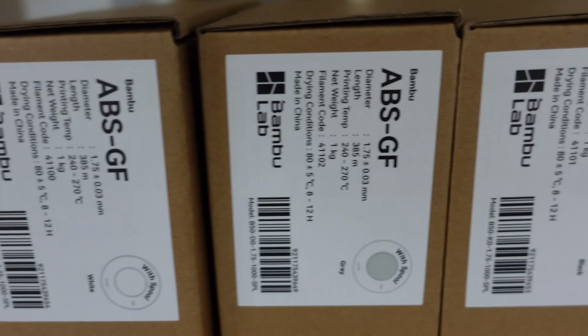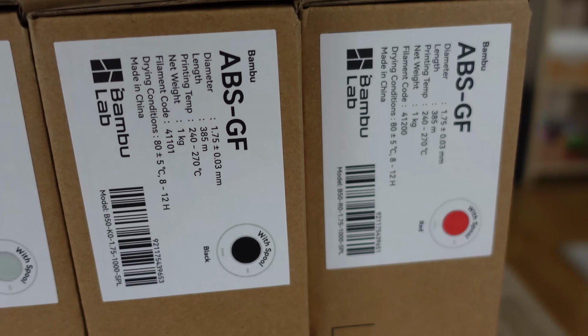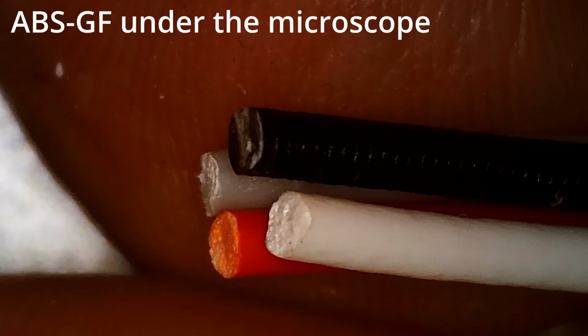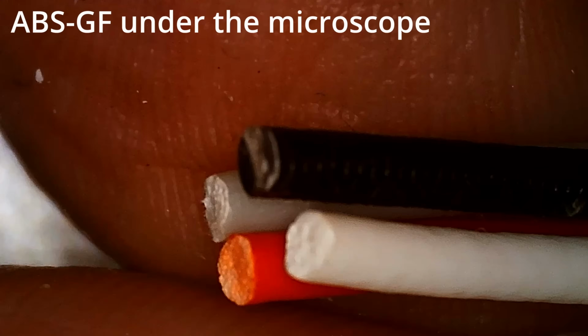Now let's talk about the glass fiber ABS. First, about my experience. I noticed that adding these fibers, glass or carbon fibers, to any material will always help with the printability. We will have less warping, so they make sense with those high temperature filaments like ABS, nylon, polycarbonate, and similar. Now, in most cases, they will make the material a little bit weaker.